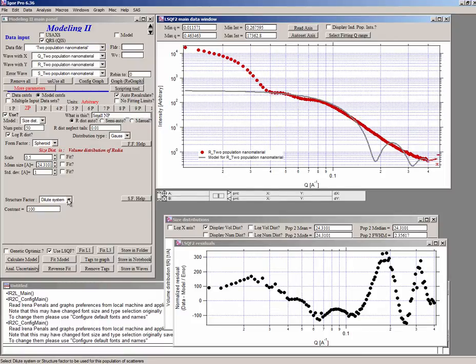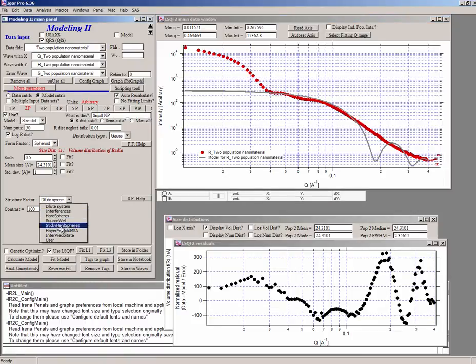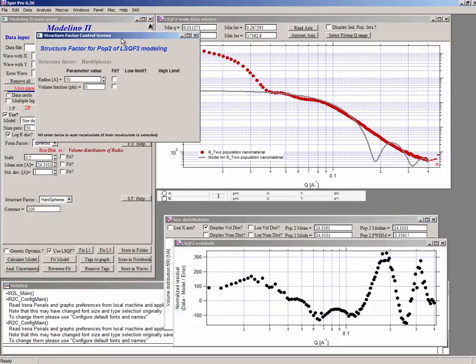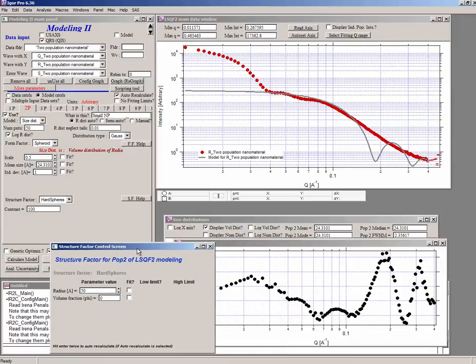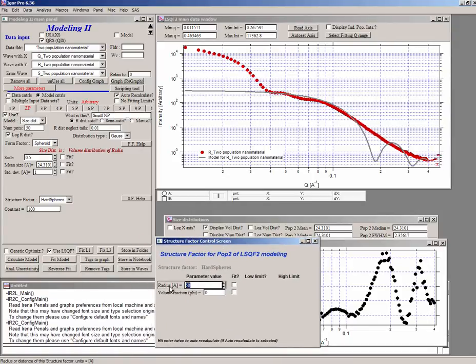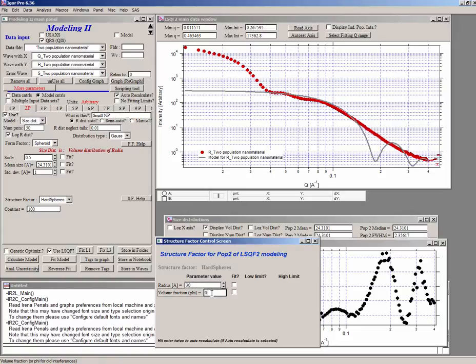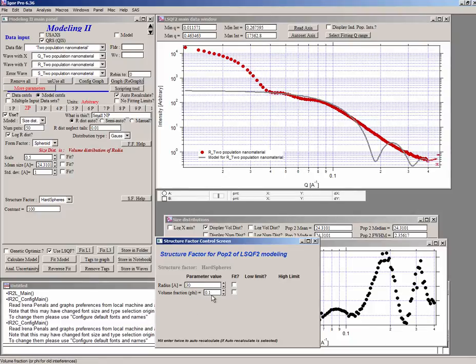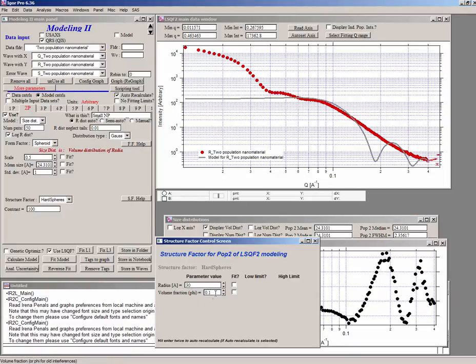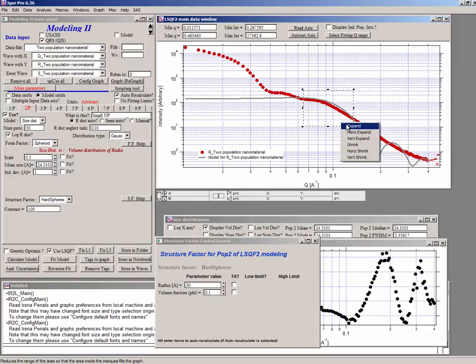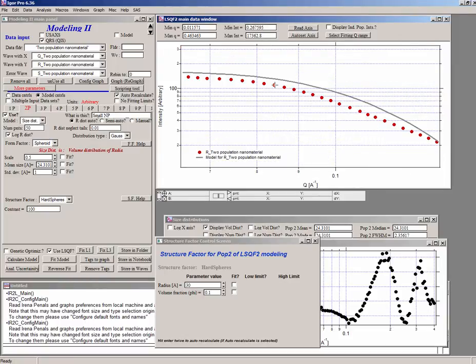To do that, to account for that, we can pull one of the many structure factors implemented here. Let's pick hard spheres. And if we pick hard spheres, I'll put it down in this area, the radius, which is the distance, the radius distance of hard spheres, should be something which is nearby the mean size. Remember this is a radius, that's a radius. So it may be like 30 angstroms. And let me put a volume fraction. This is a volume fraction, so it should be less than 0.6 or so. And for various reasons, if you want to automatically recalculate with this window here, you have to hit twice the enter key.